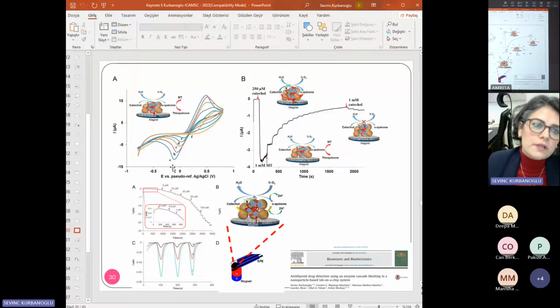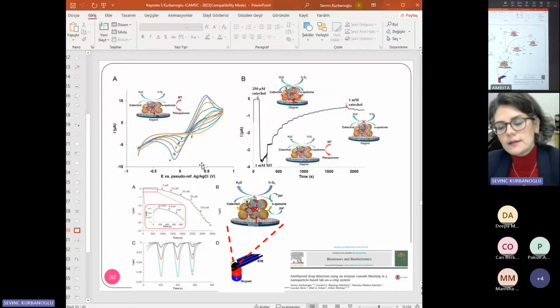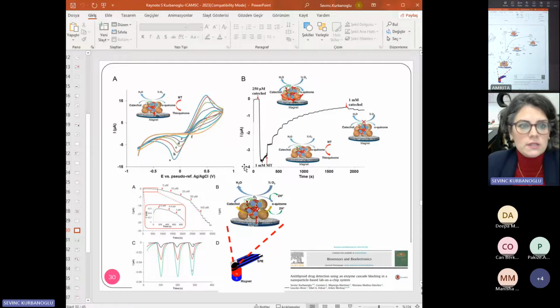So we also tried to follow this inhibition with cyclic voltammetry, and you may see here, when we add different concentrations of drug and take the CV of the catechol, we see a decrease in the catechol response. We are following the catechol response at minus 0.2 volt. And this is again proof that this drug can be used in the cosmetic sector. They can prepare a cream formulation with this drug. It was our suggestion.